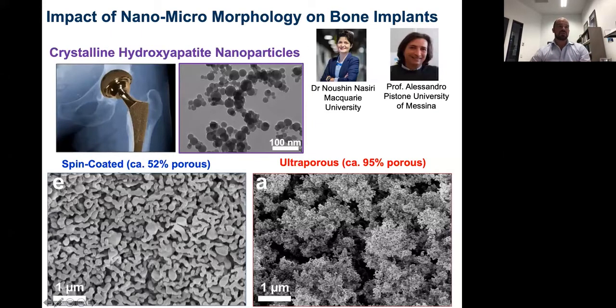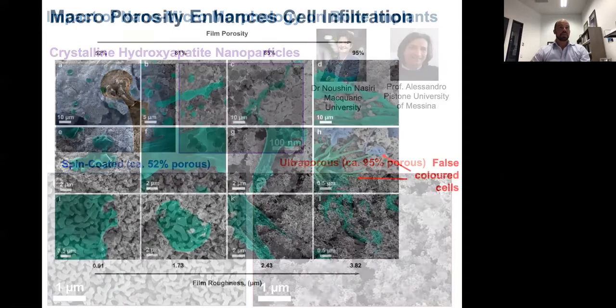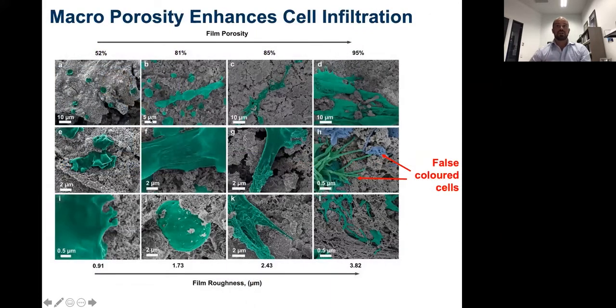And basically what they generate is this rough surface, which we've replicated here as a spin coated sample. So what we actually did is we invented a way using flame spray pyrolysis to generate ultra porous coatings of this hydroxyapatite. The idea being that we can encourage cell infiltration into these coatings and better fixation, so you don't get this loosening effect that occurs, which results in the need for revision surgeries. And I can show some pictures here of this.